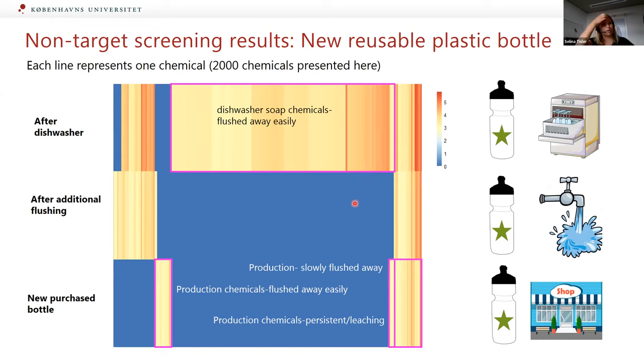The highest amount of compounds in these bottles was the dishwasher soap chemicals themselves, which were still all in after the dishwasher process when you then immediately fill up your bottle with water. But if you do an additional flushing, most of them are removed, but there are still some dishwasher soap chemicals which stick to the material and are not flushed away.